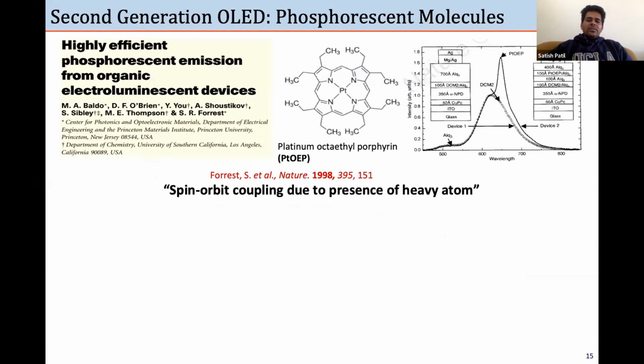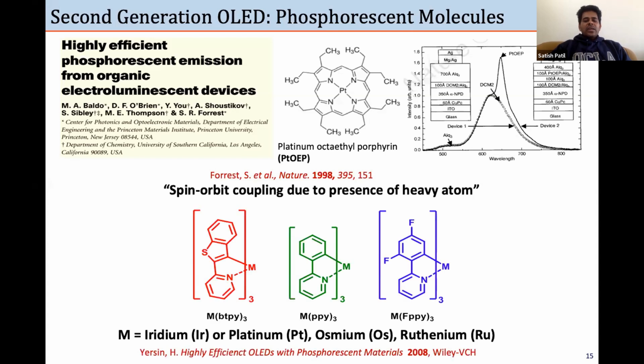To address that question, historically, this was Stephen Forrest and Mark Thompson at the University of Southern California, here in Princeton. They came up with the idea of using a hybrid material, organic and inorganic. The idea they introduced, which was well known in the literature, is spin orbit coupling, where you can use a material like platinum and ruthenium, which indeed has spin orbit coupling, and make the triplet emissive. But it turns out this is also very expensive, because these metals like ruthenium are very rare. In addition to that, there is a problem with how you process these materials. So that really did not work out very well in favor of the LEDs.